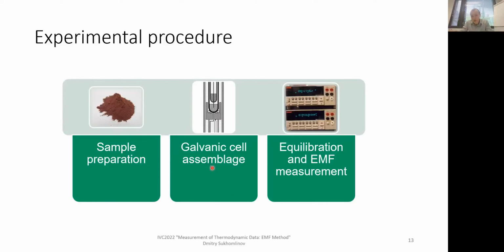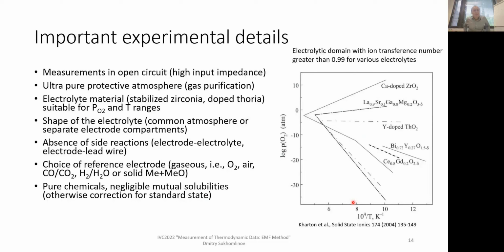Then we assemble the galvanic cell, and once it's done, we heat up the furnace and we start measurement. And there are important details which should be considered prior to building the cell and heating it up. So yes, we need a pretty good, usually rather expensive electrometer for such measurements. Then protective atmosphere for the test electrode is quite crucial, because if we have traces of oxygen in our argon gas, and these traces are several orders of magnitude higher in terms of partial pressure compared to what we want to measure, then it will just ruin our measurement.